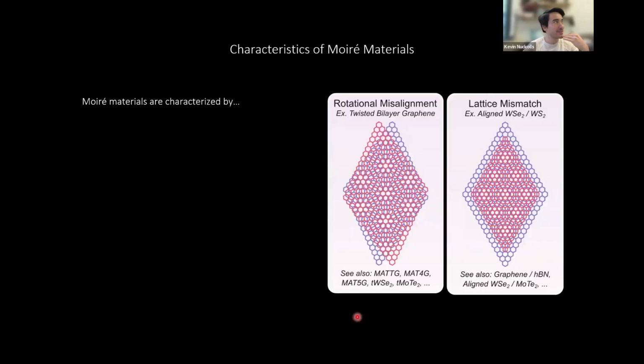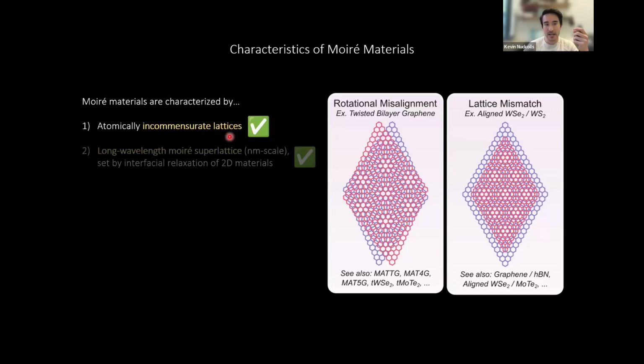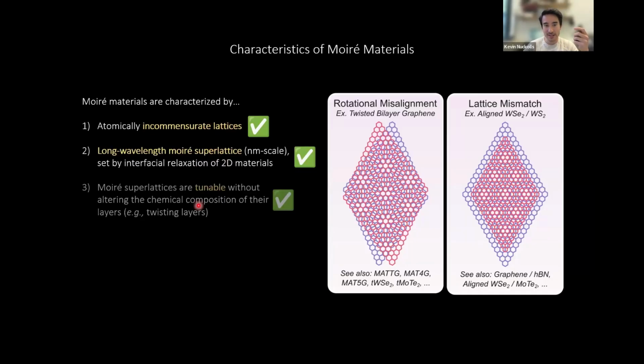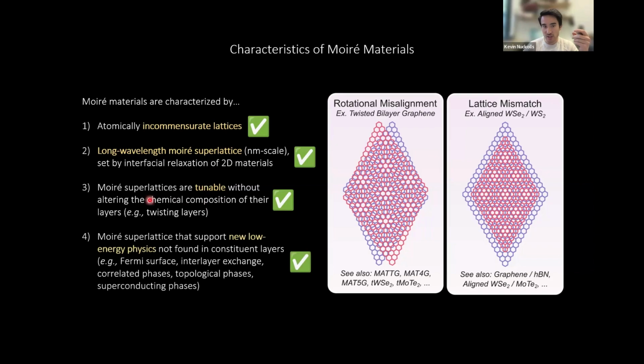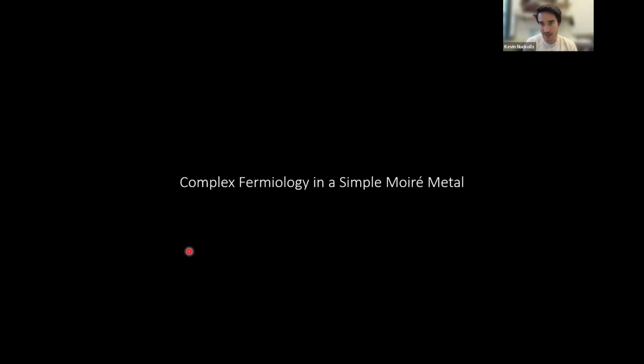So bringing this all back to the beginning of the talk, we had these qualities of Moiré materials that we should revisit. These bulk Moiré metals that we've discovered are atomically incommensurate, with long wavelength Moiré modulations. Indeed, we can tune the Moiré superlattice without trying to change any of the chemistry of the component layers. And that tunable Moiré superlattice directly imparts itself on the shape and size of the Fermi surfaces and Fermi pockets, confirming that our bulk Moiré metals have all the same characteristics as more typical 2D Moiré materials.